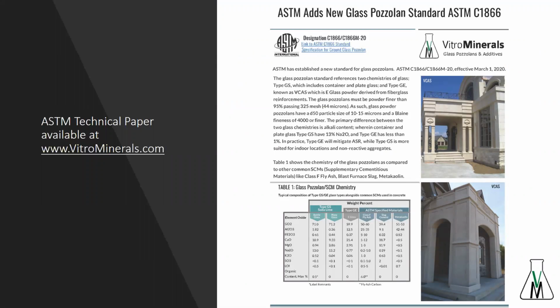On our website, vitrominerals.com, we have this document which you can download. This document has all of the properties that you can expect from glass pozzolans as compared to the properties using other pozzolans. In general, the reactivity is a bit faster than fly ash. You get a higher strength build than fly ash. In fact, our specification is 75% at 7 days and 85% at 14 days and 90% at 28 days. So we have a higher standard for the glass, and it can be substituted at 20 to 30% glass.